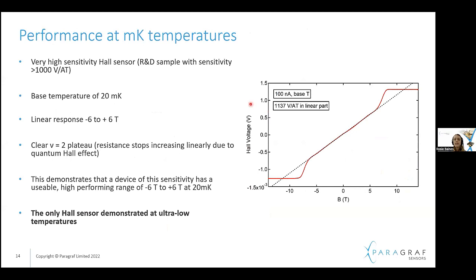So taking the temperature down a bit further and a bit more extreme, using the highest sensitivity from that range that was shown there. This is some data that was taken at 20 millikelvin. And again, we can see these plateaus start to come into play, but we see a usable linear response between around -6 and 6 Tesla.